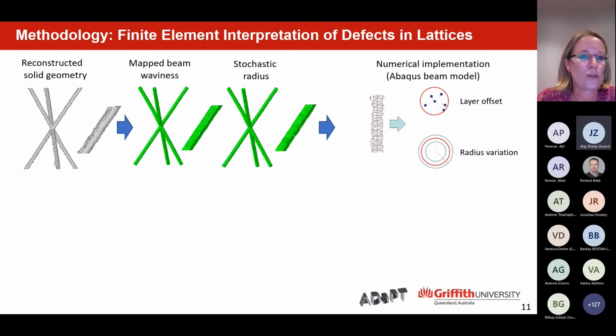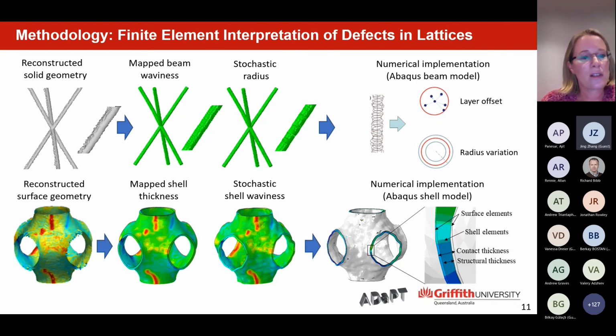We can introduce stochastic radius and radius variation. We can introduce porosity by reducing the modulus. We can introduce roughness by reducing the radius. Similarly for our shell structures, we can map the shell thickness, a bit more complex because of the surface normal, but we can map this locally. We can introduce stochastic shell waviness.